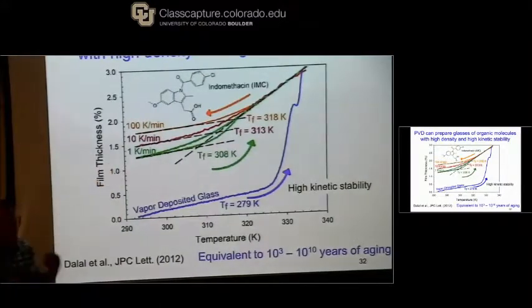So there's a molecule, indomethacin. We vapor deposited indomethacin onto a piece of silicon. So the substrate is a piece of silicon. The silicon is held at 85% of the conventional Tg. That is the Tg that you would measure by cooling at 10 degrees a minute. We deposited until we had a film that was 600 nanometers thick. So that's about 600 molecules thick.